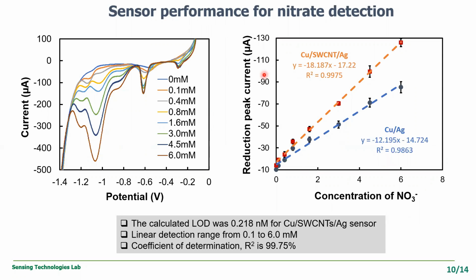Now the sensor performance for nitrate detection. In this slide, linear sweep voltammetry was applied within the potential range between minus 0.1 to minus 1.4 volt with the help of a potentiostat. A total of 8 concentrations from blank to 6 millimole of nitrate were tried. In this figure, there are a total of 5 reduction peaks visible. The first 2 are cuprous and cupric oxide reduction. And this is the one that is for nitrate reduction. The other 2 are actually for the nitrite and ammonia peaks, as this is a consecutive reaction.